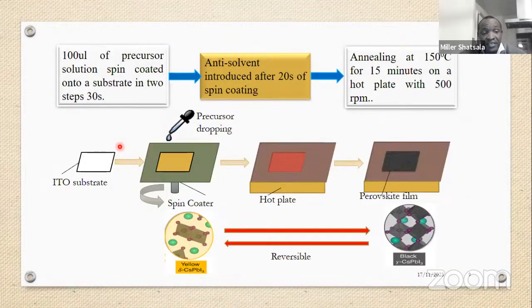Then after making the precursor solution, we shall clean our substrate, and mostly we use the ITO substrate. Then we shall take 100 microliters of the precursor solution and drop it on the ITO substrate, which has been placed on a spin coater. Then we spin coat it for around 30 seconds. At this stage, when we have spin coated this film, it will be yellow in color. That will give us the yellow phase of the perovskite film precursor.